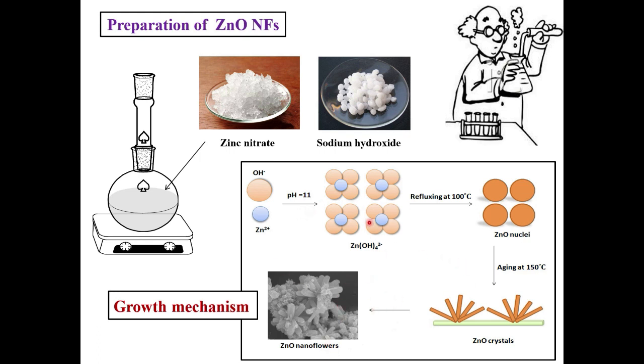It is a simple mechanism: from zinc nitrate and sodium hydroxide to zinc hydroxide, then refluxing at 100 degrees centigrade forms the zinc oxide nuclei. Aging at 150 degrees centigrade causes growth of the crystals along the c-axis. These crystals grow along the c-axis, come together, and form the zinc oxide nanoflowers.